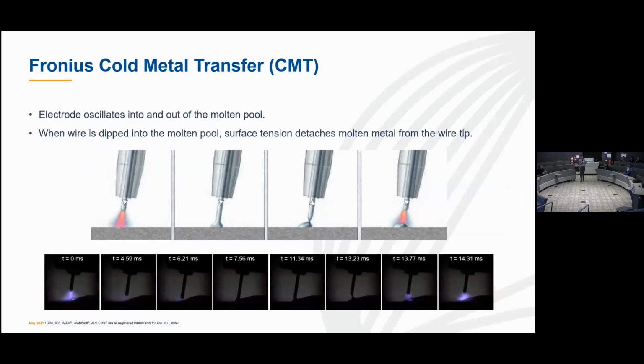So you have a torch. On the left-hand side there, you've got an arc created between the end of the wire and the substrate. Now, the unique aspect of the CMT is that the wire, rather than being constantly fed into the molten pool, pulses backwards and forwards. So you have the arc that's created, that wire is then thrust into the molten pool, and that molten material is then deposited by surface tension, and then that wire is retracted backwards. Quite unusual. Most welding processes, that's just a constant wire feed. So when the wire is retracted backwards, you then recreate the arc, and then the whole process is repeated.